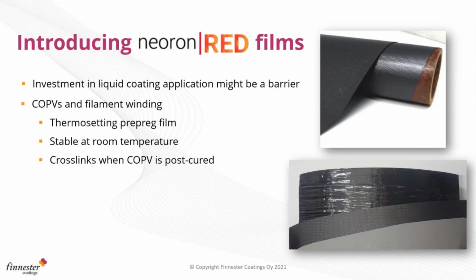So this neoron RED film is designed for pressure vessels, especially for filament winding. It's a thermosetting pre-preg film, which is stable at room temperature, meaning that it's not tacky. You don't have to freeze it. It's like a film, and you can apply it during your filament winding process. You can apply it as the last surface on your filament wound piece, and you will need two different products. You will need the thermal insulation film, and then you will need the ceramification film. Here you can see the black film, that's the thermal insulation film, and the gray on top is the ceramifying film. All these together will give you that protection.